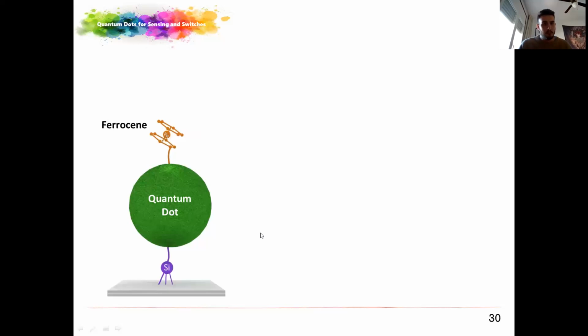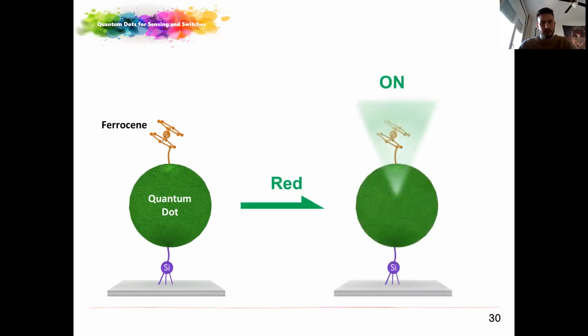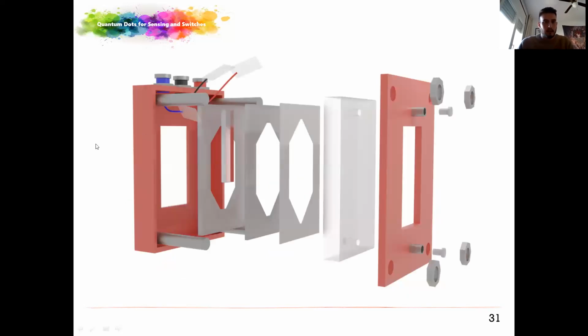Following this strategy, in my group we are trying to develop a new surface for switching applications using quantum dots attached to a silane on a conductive surface, which is ITO, with a fluorophore attached on the surface of the quantum dots. In our case, we don't want to use a multilayer, just a monolayer. And we hope that after the reduction we observe an increase of the fluorescence, and after the oxidation, a decrease. It's an on-off situation.